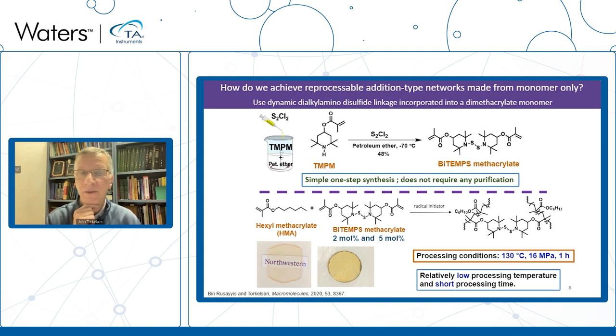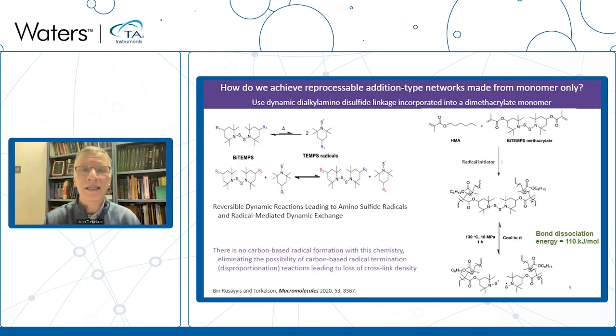This particular network we can reprocess at 130 degrees C and make into new materials. So the idea here is we do our reaction of hexyl methacrylate with BiTEMPS methacrylate, about 5 mol percent of BiTEMPS methacrylate in the system. We add a radical initiator, just do free radical polymerization, but because there are two carbon-carbon double bonds here, we actually make a network. And then we can reprocess this network at 130 degrees C.